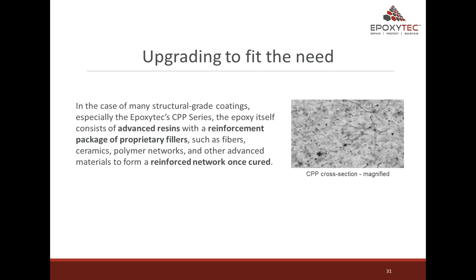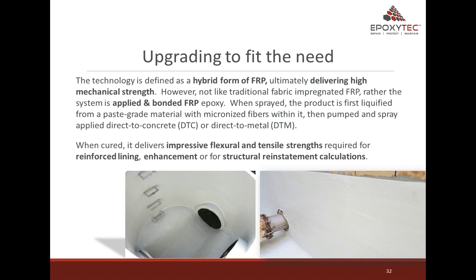In the case of many structural grade coatings, especially Epoxytec CPP series, the epoxy itself consists of advanced resins with a reinforcement package of proprietary fillers, such as fibers, ceramics, polymer networks, and advanced materials to form a reinforced network once cured. The technology is defined as a hybrid form of FRP, ultimately delivering high mechanical strength. However, not like traditional fabric impregnated FRP, rather the system is applied as a bonded FRP epoxy. When sprayed, the product is first liquefied from a paste grade material with micronized fibers within it. Then pump and spray applied direct to concrete, DTC, or direct to metal, DTM.